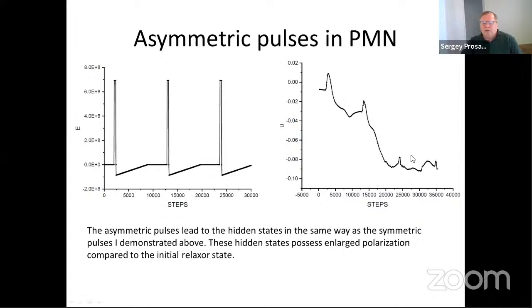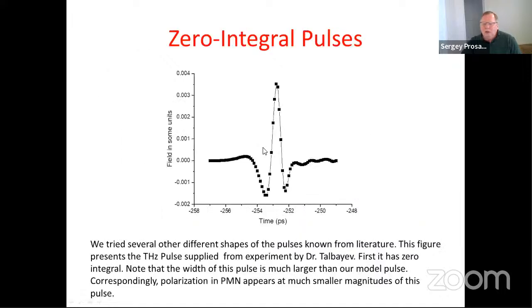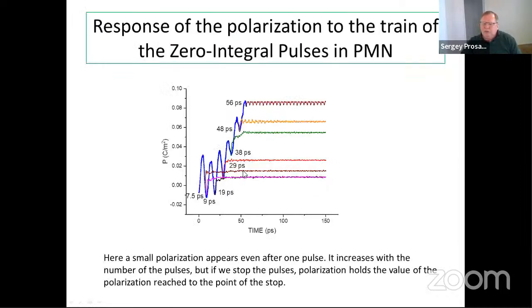So we also tried asymmetric pulses, and the result is the same in the sense that we had intermediate states after each pulse. These states are different. We also tried an experimentally designed electric pulse, which was supplied to us by Dr. Talbayev, our co-author. And this pulse is interesting because it has zero integral. And again, we found with this pulse these intermediate hidden states. After each pulse, we have a different state.